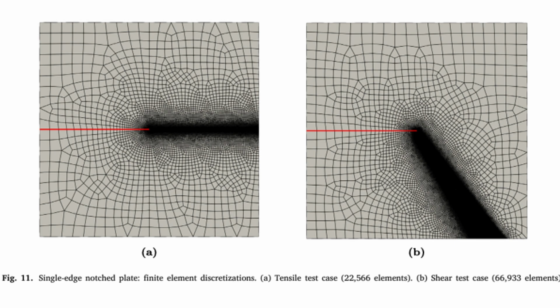Exactly. And they tested it with 2 common phase field formulations, the AT2 model and a cohesive zone model, CZM-inspired one, and compared it directly against the traditional robust AM algorithm. And the big headline, the 5 times speed up. Did it hold up? It absolutely did. Across all examples, all models, the L-BFGS algorithm combined with the new line search consistently delivered an average computational time saving of around 5 times compared to the AM method. 5 times faster on average.